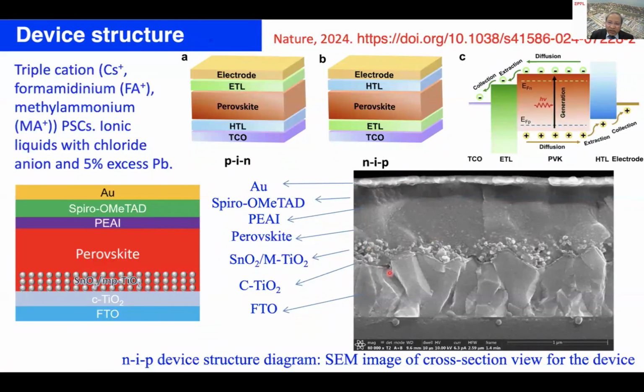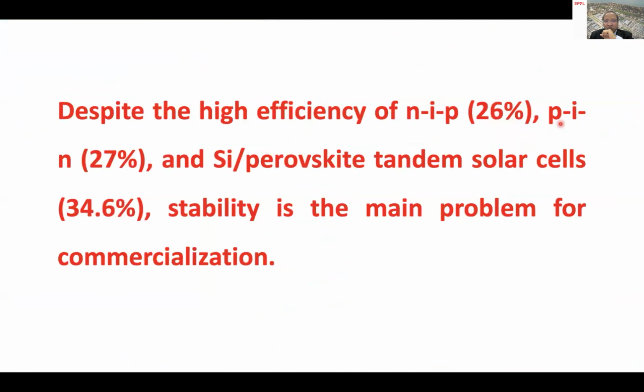So here I'm showing a typical example of a cross-section image of a perovskite solar cell, where we have a conducting glass. On top, we deposited electron transport material. This is NIP configuration, and we deposited perovskite, which is typically 600 nanometers, followed by a very thin layer of 2-dimensional perovskite. I will give you this in the later introduction. Followed by the hole transport material. This type of efficiency, NIP and the PIN configuration, will come in the later slides.